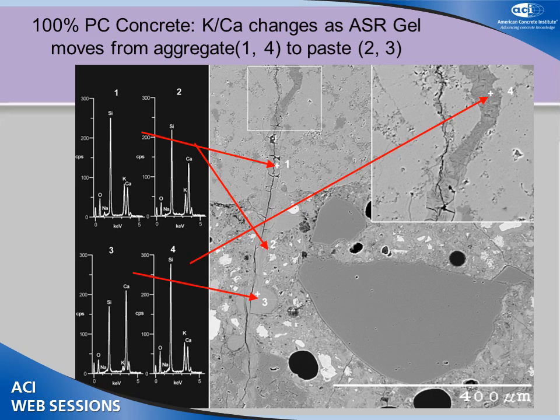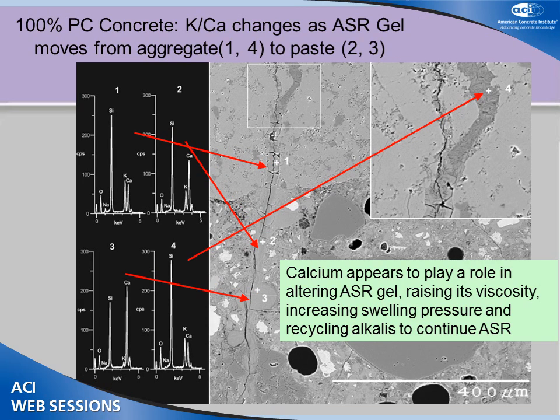But then as soon as it gets out into the paste, we're starting to see more calcium relative to potassium in the gel by EDX. And as you get further out into a void here that's been filled with gel, we see much higher calcium and less potassium. So we're seeing this change in composition of the gel as it exudes into the paste, as some of the alkalis are being recycled and calcium from the paste replaces the alkali in that gel, which has been associated with swelling pressure by changing the viscosity of the gels.